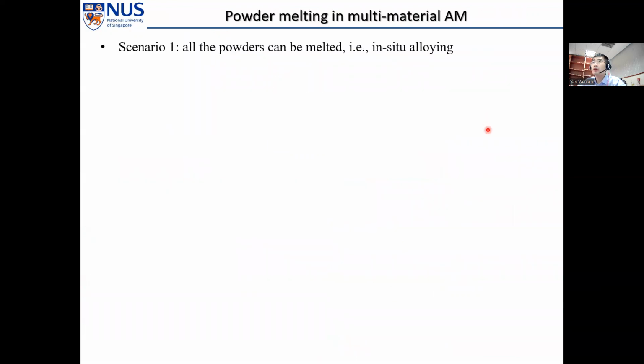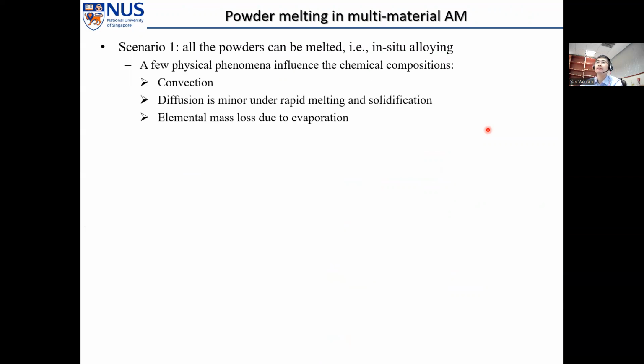Now for powder melting in multi-material additive manufacturing, which is very promising in material design, there are two scenarios based on our consideration. One is where all the powder is melted. That is actually in situ alloying. There are a few physical phenomena that influence the chemical composition and should be considered. One is convection; diffusion is usually minor, but there is also rapid melting and solidification, and elemental mass loss due to evaporation is also serious.